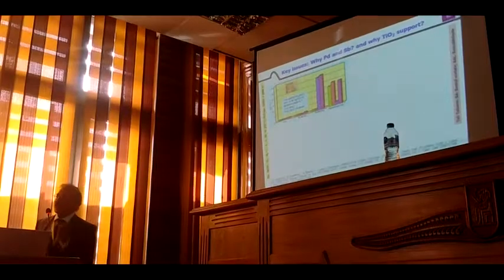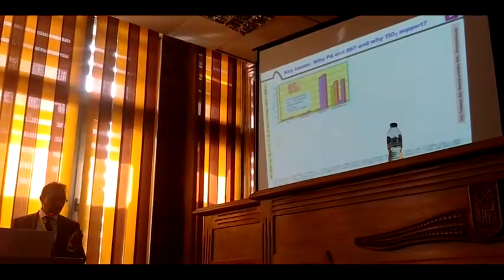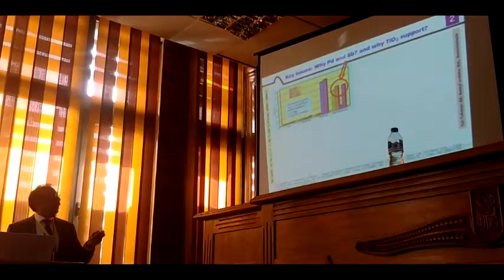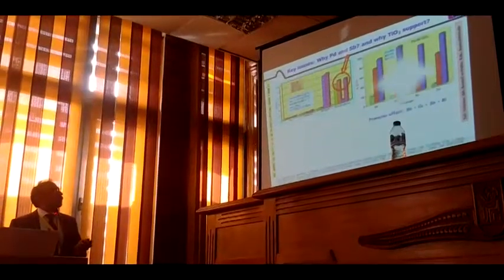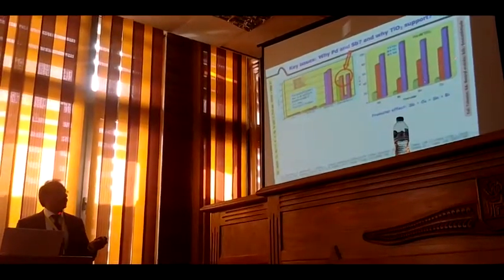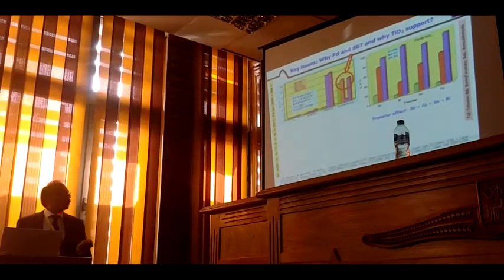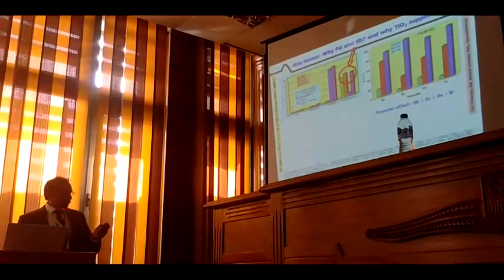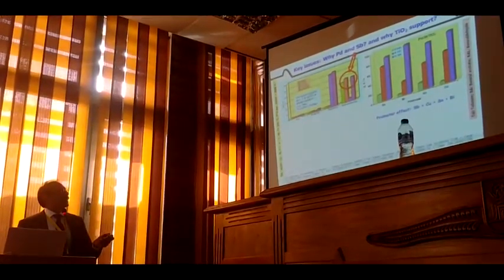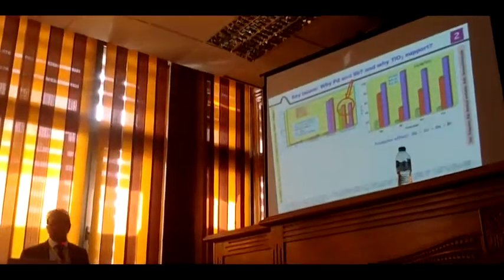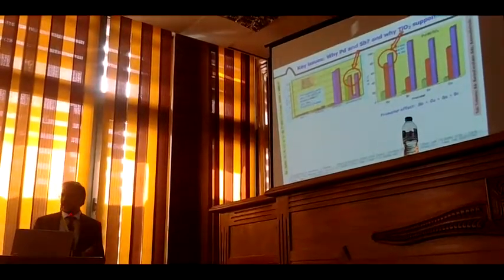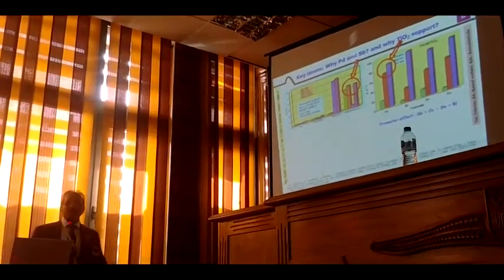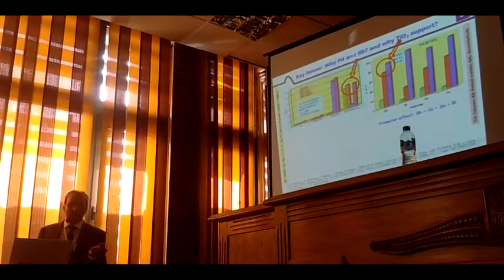Then you may ask, why only antimony? Why not other promoters? So we have tried a variety of promoters. I can show you here. So of course we are convinced now this palladium antimony combination is essential. So when we changed other promoters, antimony, bismuth, tin, copper, and so on, you can again see the red column and blue one. So the conversion is highest in case of antimony compared to other promoters. This means antimony is necessary. Then you ask, why titanium? Why not other supports? The selection is purely based on performance.